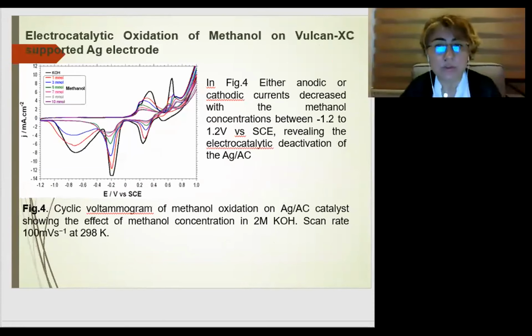The effect of the methanol concentration on the cyclic voltammograms of the catalyst with a potential sweep rate of 100 millivolt per second was investigated, and the results are presented in figure 4. The methanol concentration was changed from 1 millimolar to 10 millimolar. It is shown in this figure that the methanol oxidation peak current density decreases with increasing methanol concentration. Thus, the adsorption of the oxidation products at the electrode surface hinders further oxidation. Either anodic or cathodic current decreases with increasing methanol concentration.